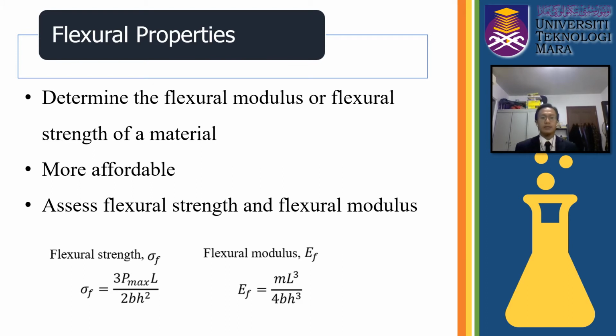The most common aim of the flexure test is to assess flexural strength and flexural modulus. Flexural modulus is determined from the stress slope versus the strain deflection curve. These two values can be used to test the ability of the sample material to withstand the flexure or bending force. These are the flexural strength and flexural modulus formulas.